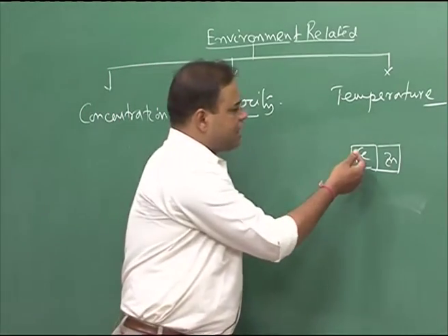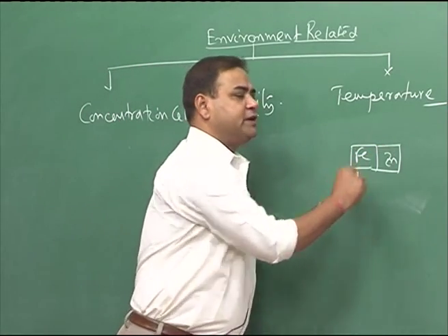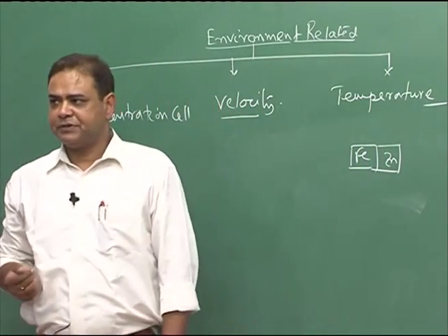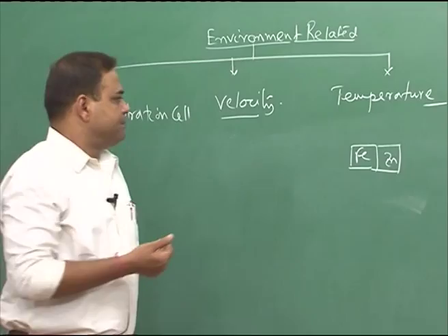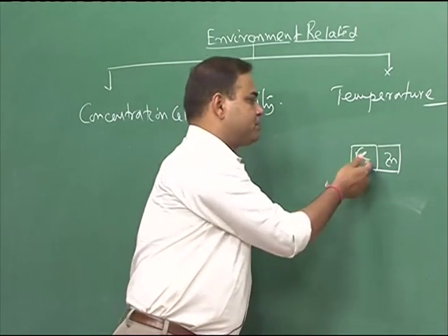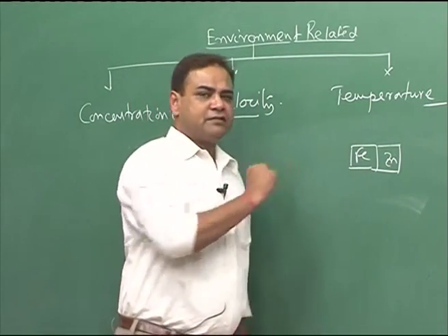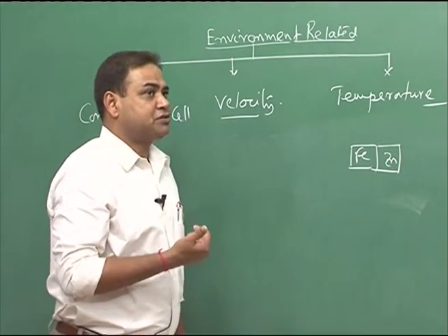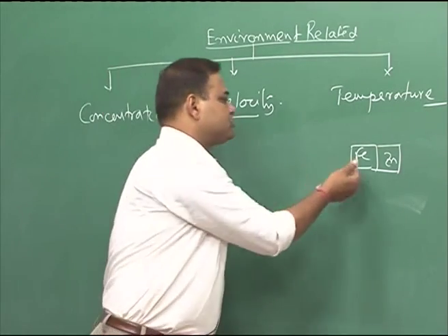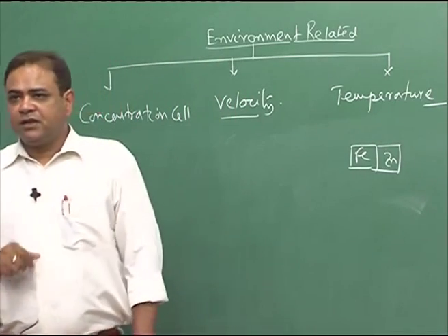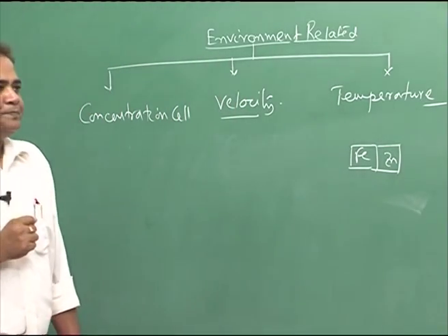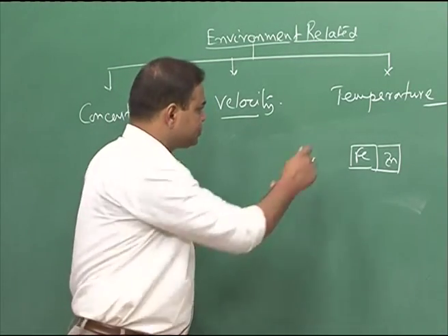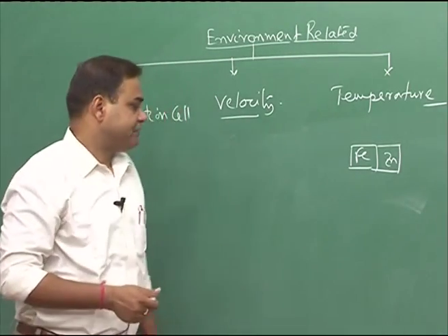In that case iron will corrode and zinc will be protected, since the zinc oxide layer has formed above some critical temperature, and that leads to corrosion of iron instead of protection. So, temperature is another issue. If we increase the temperature, in most cases the corrosion rate increases, but there could be a possibility of polarity reversal due to the formation of a different passive layer. So, this is the temperature factor.